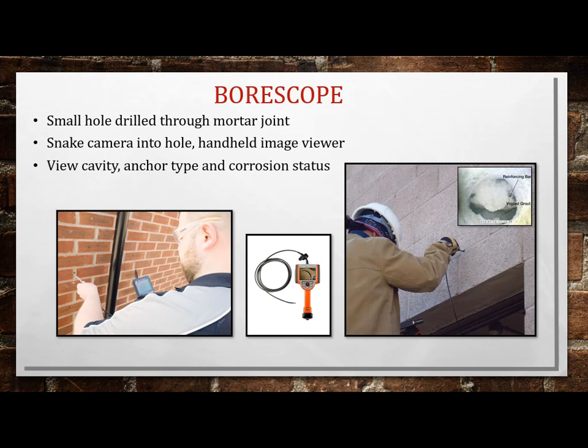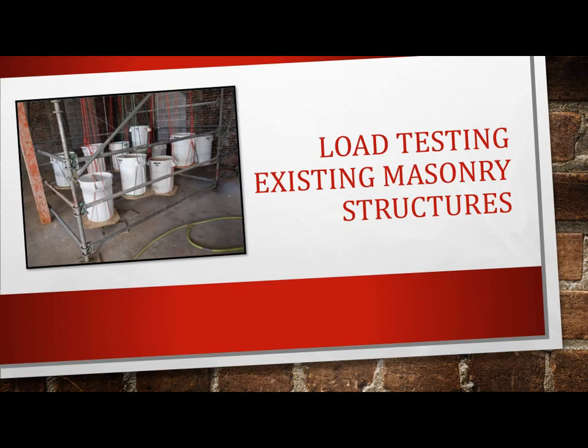Another test is borescopes. So that 3/8 hole we drilled, you can push a borescope in there and look around, look for corrosion, look for what kind of anchor types. It's real good to look in the cavity between the veneer and the CMU block. We're curious what's in there, what kind of anchors. Is it wet? You hope it's not full. You don't know. You can measure it. Borescopes are pretty cheap. You can buy a borescope now for $200 at Lowe's. It's not a real good one. Real good ones are multi-$1,000, but for a quick test, that'd be okay.